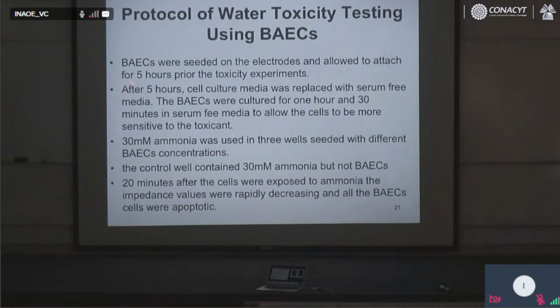The cells are like us, they eat something from the nutrient, and in order for the cells to be sensitive to the ammonia, they need to be very hungry, to starve. So it was really hard. You need 5 hours before the experiment to change the media in the cells, which contains the nutrient, with only serum, like water. And they stay 5 hours without any food, or only with serum. They are very weak, and then you need to introduce the toxicant inside. And we introduced toxicant with different concentration, and the cells were really sensitive.